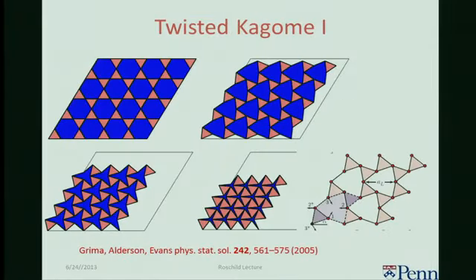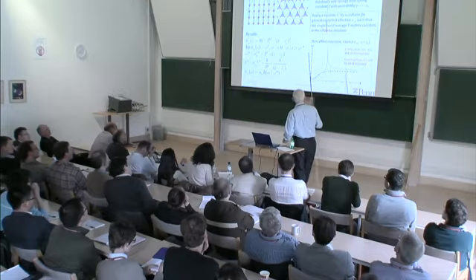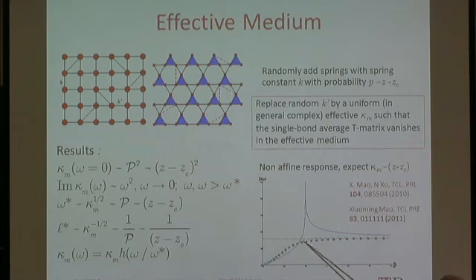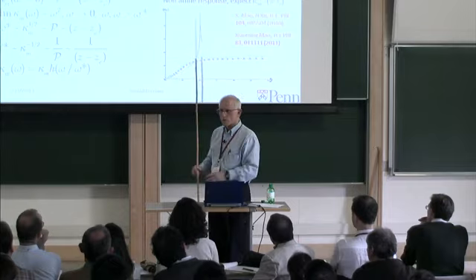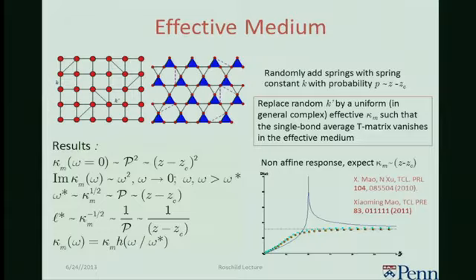But there's another interesting question about these. You might, however, worry, and it's very similar to mean field theory in many ways, right? You might worry about whether this works. The blue dots are the effective medium theory. The red dots are simulations. So it's pretty good. You might worry, but it really works much better. And there are many other instances we've done now where it fits simulations. It works particularly well if you put in bending and you dilute the Kagome lattice, you get the effects of adding bending described fairly well.